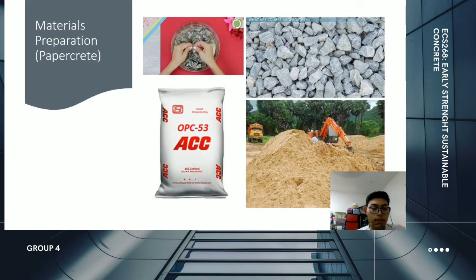Alright, so this is the materials preparation for papercrete. In our laboratory activity, we use coarse aggregate and fine aggregate, which is river sand. The coarse aggregate is a maximum of 20 mm in size, and we use OPC 53, which is a specific grade. And lastly, we use paper pulp that we sink in water and wait until the paper degrades into paper paste, and then we dry the paper paste and grind it into paper pulp.